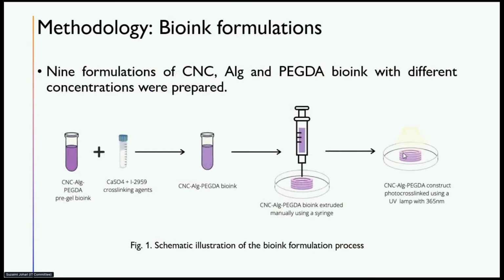Next slide. For the second part is the bioink formulations. So 9 different formulations with different concentrations were prepared. They were prepared separately and then they were mixed together to form a homogeneous pre-gel bioink. And later they are added with the cross-linking agents, which is the calcium sulfate and the photoinitiator, to form a gel bioink. Now this gel bioink is then loaded into the syringe and the constructs are then extruded based on the desired shapes that we choose. And after it is extruded, we then subject it to UV light under 365 nanometer wavelength.